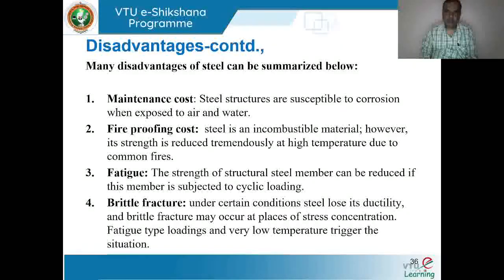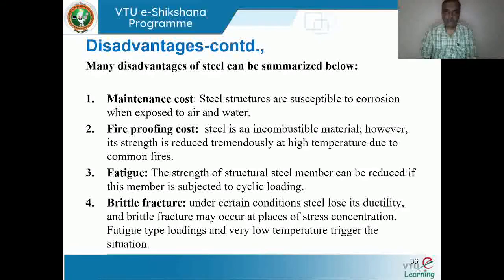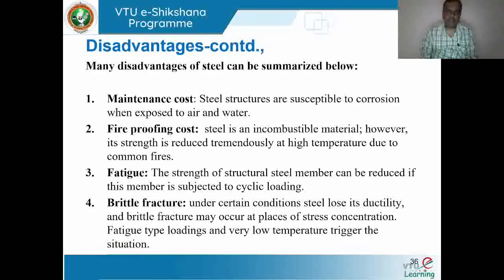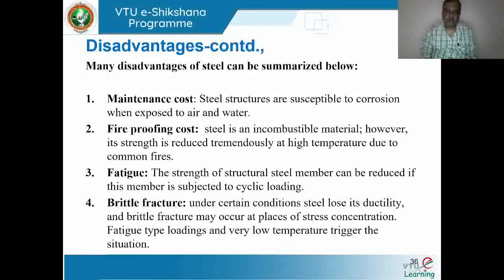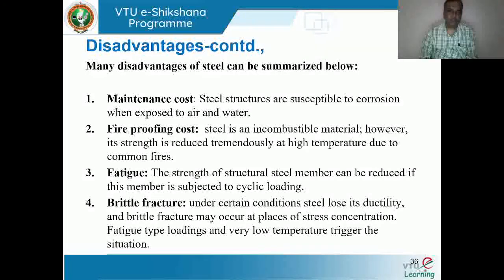Steel is an incombustible material, but however its strength is reduced tremendously at high temperature due to common fire. So when there is a fire hazard, the temperature increases beyond 500 to 800 degrees centigrade, and at that temperature the yield stress of the material decreases substantially. An increase in temperature up to 100 to 200 degrees centigrade definitely causes substantial deformation, elongation, but the yield stress may not decrease considerably. But when the temperature increases beyond 500 degrees centigrade and goes up to 1000 and even more than that, the yield stress of the material decreases, and sometimes it will be as low as 10 to 15% of the yield stress.